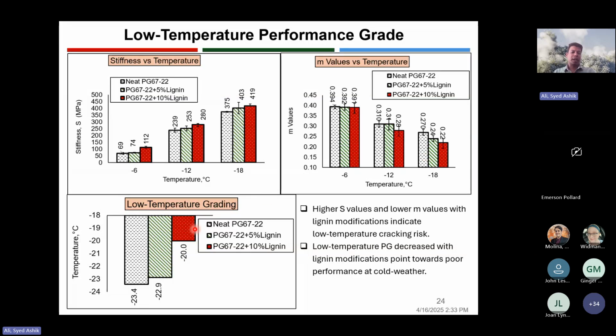We wanted to see how the amount of lignin impacts the low temperature performance grading. As you can see, initially the PG 67-22 binder had a continuous grade of -23.4. After the addition of 5% lignin, it didn't change much. It's still a -22 binder with a continuous grade of -22.9. And when we added 10% lignin, that changed quite a bit. With the addition of 10% lignin, it went up to -20 degrees Celsius. So around 3 to 4 degrees Celsius change in the low temperature grade. That also indicates that low temperature cracking, or the use of this asphalt binder at low temperature, may be an issue.